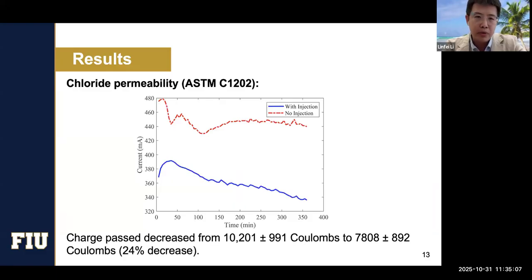Again, we also did some chloride permeability testing. Imagine if you have a lot of pores and your sample is fully saturated, that means you have relatively higher electroconductivity. But silica is more like what we call a semi-insulating material. So if you have nanosilica sealed in the pores, the charges or electrons will not be able to pass by. That's why we did the test, one untreated sample with no injection, the other with injection. As you can see, there is a clear trend as well. The charge passed, or the current passed, is significantly lower, about a 24% decrease, which means the chloride ions are not easy to transport from one side of the sample to the other once you apply the external current, just because of the injection of nanoparticles.